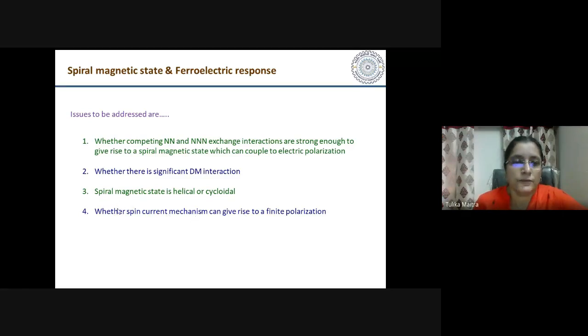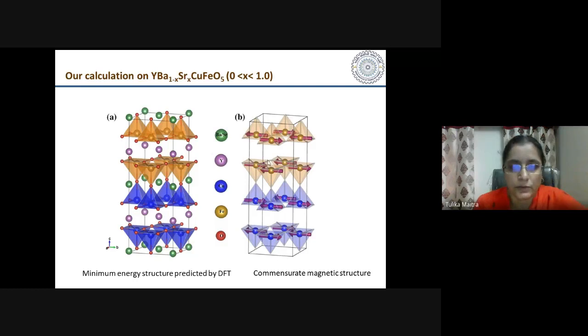So these are the few issues that have to be addressed, and one can address these issues by doing density functional theory calculations, which we have done for this system. And what we find is that the density functional theory calculation gives you this structure as the minimum energy structure.